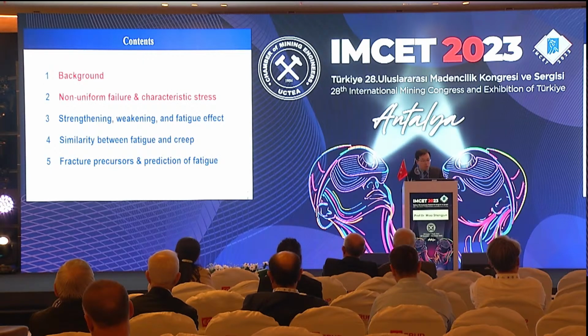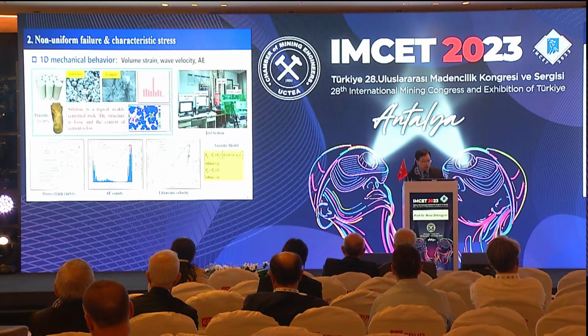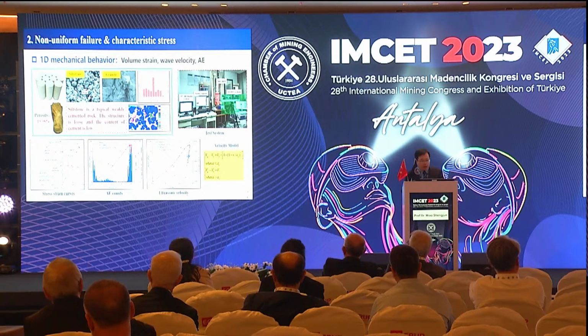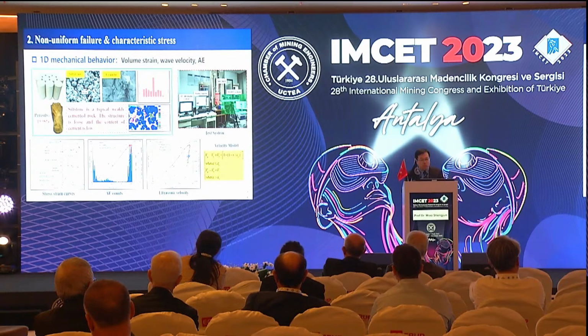Part 2, multi-dimensional non-uniform failure and characteristic stress of rock. First, we studied one-dimensional mechanical behaviors of siltstone. Here, one-dimensional refers to certain non-directional physical quantities, including volumetric strain, wave velocity, and acoustic emission counts. The siltstone we studied has low hardness, small particle size, and high porosity up to 20%. The initial wave velocity is only about 2,500 meters per second.